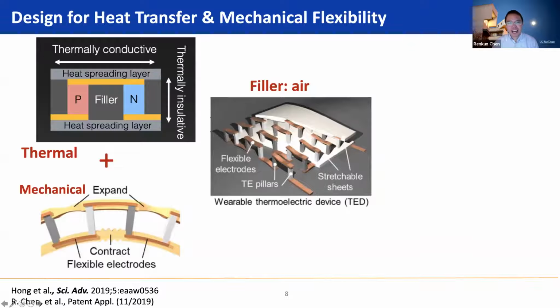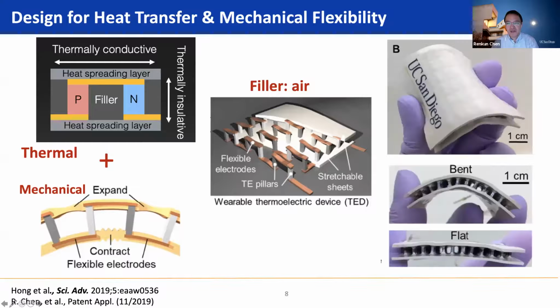So this is a 3D schematic of the device we eventually made. And in this case, we actually use air as a filler to improve both the thermal insulation conditions between the hot side and cold side, as well as the mechanical flexibility. And again, you can see we have these elastomers at the top and bottom as the two layers to sandwich these N-type P-type pillars. And also these elastomers have enhanced thermal conductivity by embedding thermally conductive fillers like aluminum nitride, ceramic particles into this polymer. And again, here shows the regular thermoelectric pillars. And these are the photos of this design, this designed thermoelectrics. And as you can see, they are flexible.